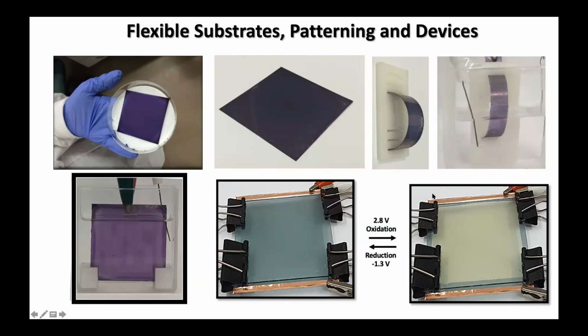When you oxidize the film at high potential, 2.8 volt, the film becomes transparent and you can reduce it back to the starting point. What is unique about these materials is that they are dark. They are very non-transparent in the ground state, and they become transparent only when you apply a voltage. Many materials like electrochromic organic polymers are non-colored in the ground state and become colored when you apply a voltage. Also, the dark state is often a problem in this field, but in these films, as you can see here, we can make them completely dark, so you cannot see through them.